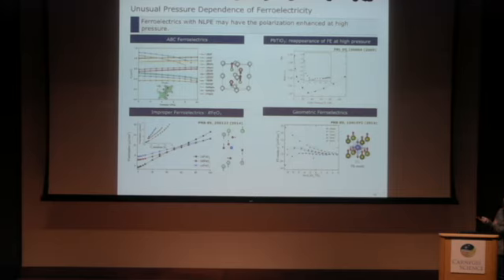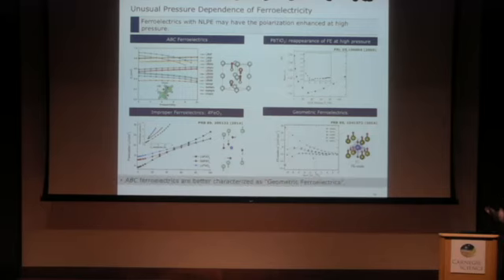However, for ABC ferroelectrics, it's a proper ferroelectric characterized by a zone center mode. So in this paper, they also look at polar instability for some geometric ferroelectrics. Indeed, for some geometric ferroelectrics, what I calculate is the square of the TO mode frequency as a function of pressure. This is the high pressure region. As you can see, the polar instability indeed gets enhanced with increasing pressure. So within this picture, I think ABC ferroelectrics are probably better characterized as geometric ferroelectrics.